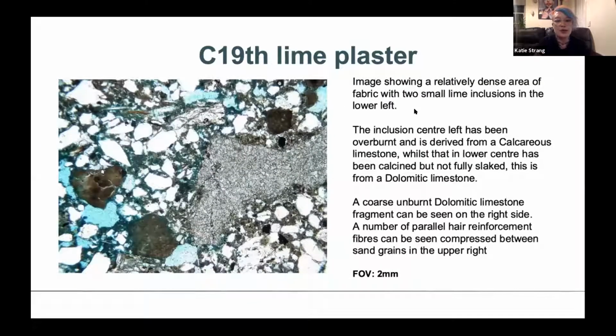And this image here shows quite a dense area of the fabric, and there are two small lime inclusions in the lower left here. And this here is a bit of limestone, which is a dolomitic bit of limestone, and this is calcined, but it's not fully slaked there. But in these lime inclusions, you can see the cracking which is observed there, and this is the dolomitic particle of limestone there. And there's some hair reinforcement. You can quite often see that in thin section, which is up there in the corner. And depending on what angle you've made the thin section, it can form some quite cool structures in there.